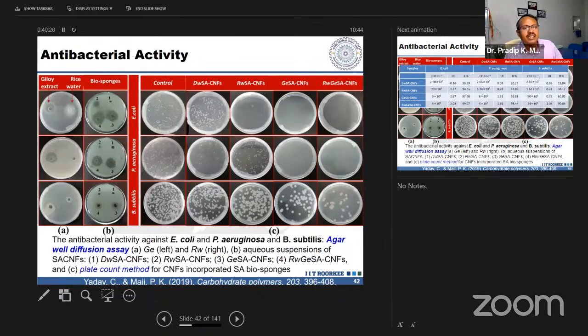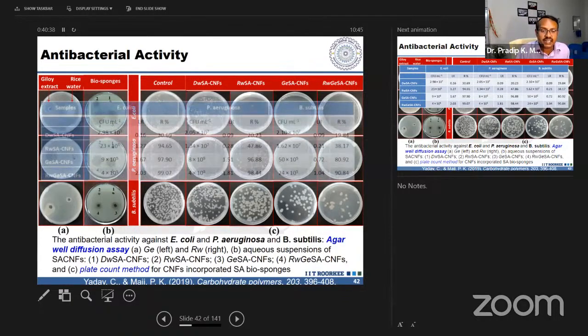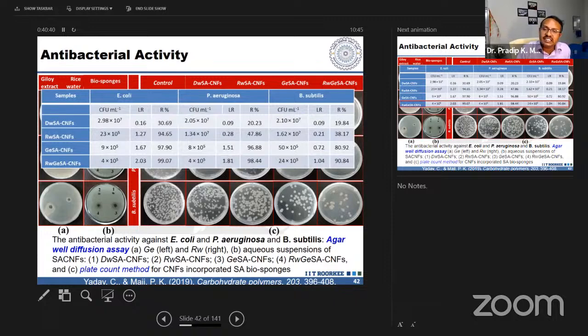We have checked the antibacterial property, and for your information, the combination of this material is giving very good antimicrobial property. We have tested 3 different types of bacteria, both gram-positive and gram-negative, and all give very good results. We checked with the colony count method, and everything is as per what I have shown in the photograph. Similarly, the sodium alginate, rice water, and giloy water along with the CNF show very good results.